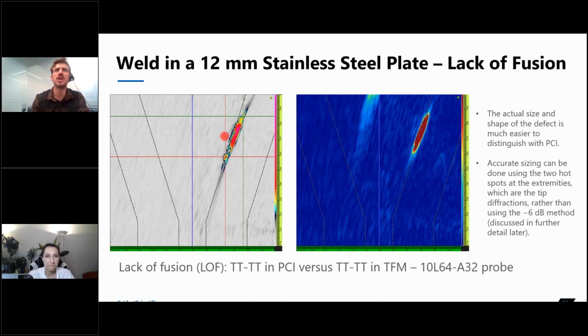But with PCI, what we notice is that usually our background noise is from 10 to 15%, so we want to have that gray in the background. But actual interesting defects started to be around 30% coherent. So that's why we started to have that more punchy color around 30%. And we wanted to have a color that's contrasting a bit higher so that it really stands out. So the effect that it makes is we have that red, which we're used to seeing, but slightly different so that we know to look there.